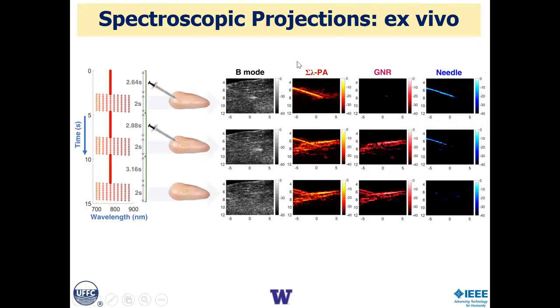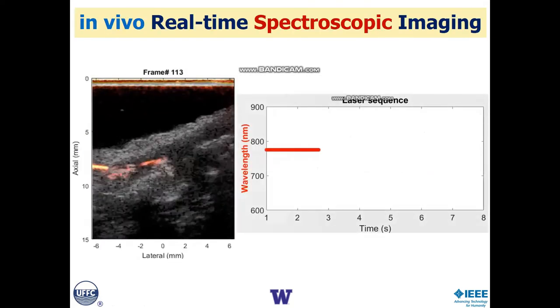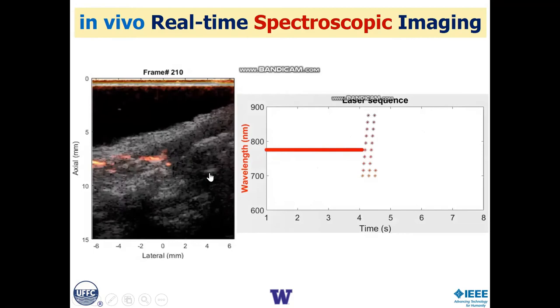These are the conventional ultrasound and conventional photoacoustics. Here is the projection onto the contrast agent, so we see just the contrast agent image. Here is the projection onto the needle, and so we see just the needle image, and it follows the experiment. When we stick the needle in at the beginning, we see just the needle. When we inject the agent, we see agent plus needle. When we remove the needle, we just see the agent. True molecular imaging.